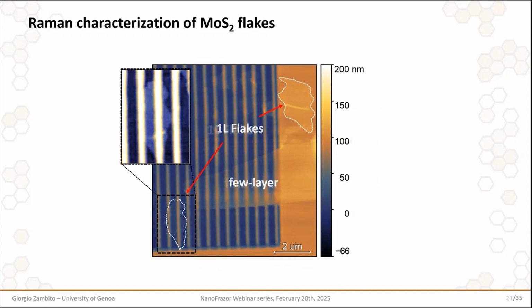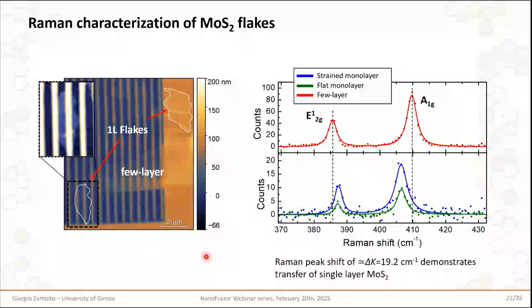And the fact that we are actually observing monolayer MoS2 is confirmed by Raman microspectroscopy, where we observe that the vibrational features of MoS2 lie in the right and expected spectral regions, and also that the monolayer flakes present a spectral shift of around 19 cm^-1, so coherent with the presence of monolayer MoS2.